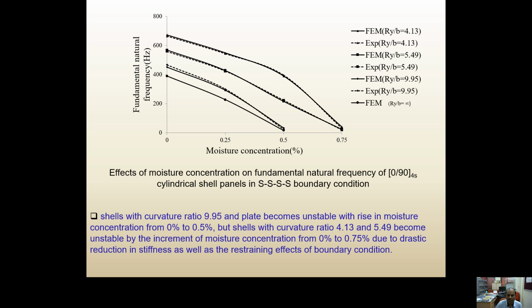Similarly, studies are also conducted for moisture concentration. The moisture is varying from 0 to 0.75%. The shell panels are, as you can see, affected significantly with the increase of moisture at 0.5 moisture concentration. So the plate and the shallow shells are coming to nearly negligible stiffness. Similarly, at 0.75, the shell panels are coming to negligible stiffness.